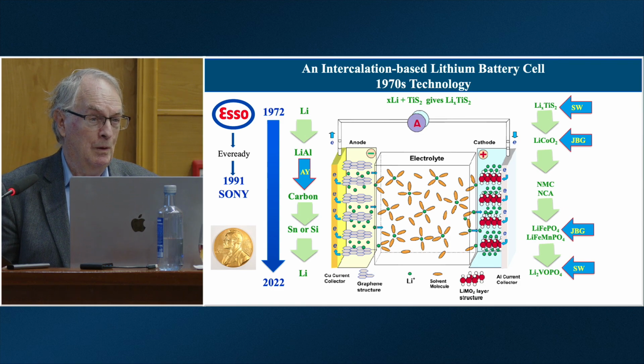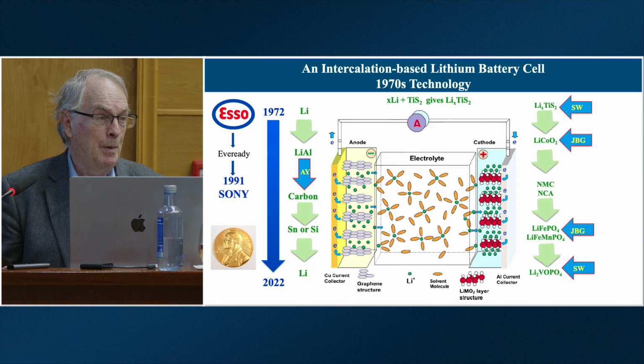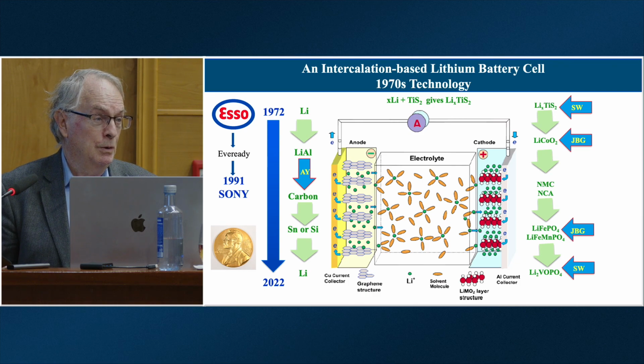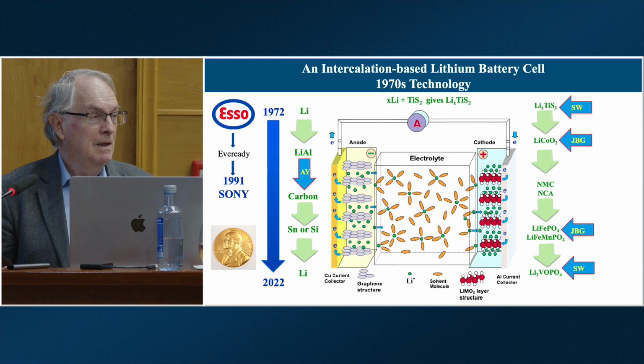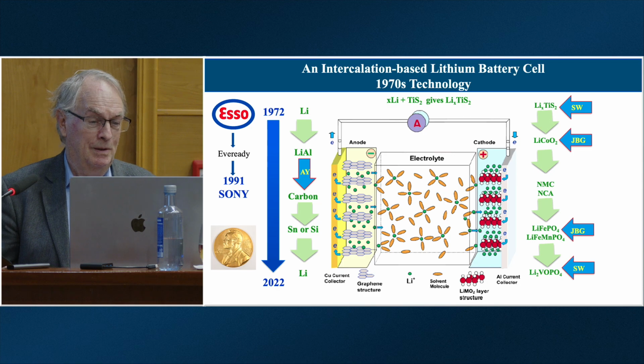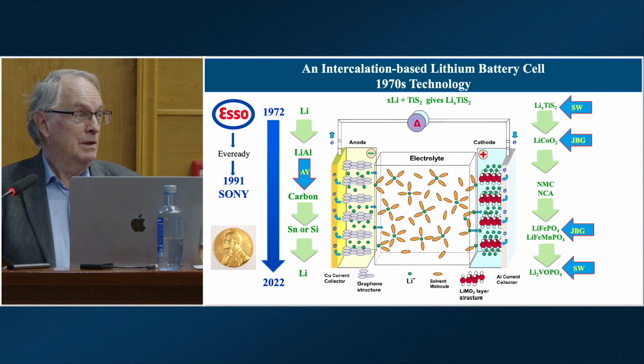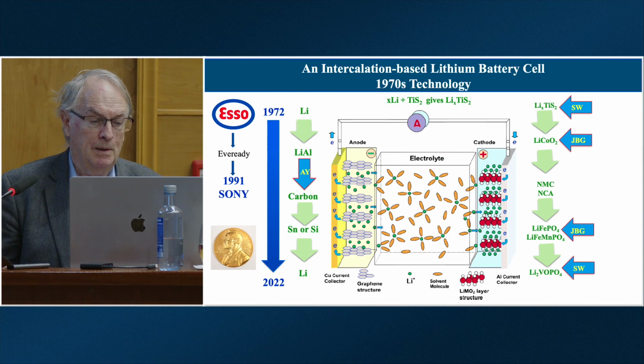And if you've got an iPhone or any smartphone, any small device, the cathode is still lithium cobalt oxide. But the cobalt is far too expensive. Most of it comes from the Congo, and half of what comes from the Congo uses child labor. So there's a huge push to get cobalt out of the batteries, and so the most common compounds used today are mixtures known as NMC or NCA. That just means nickel, manganese, cobalt, or nickel, cobalt, aluminum. So we're trying to reduce the cobalt in there.